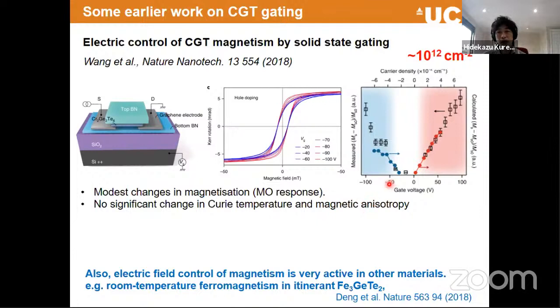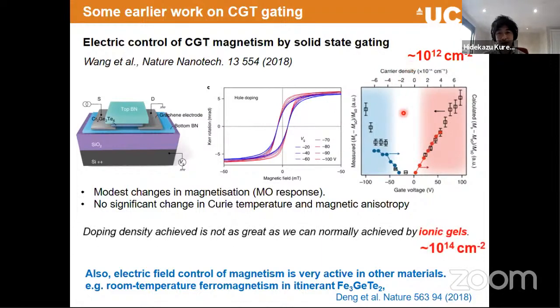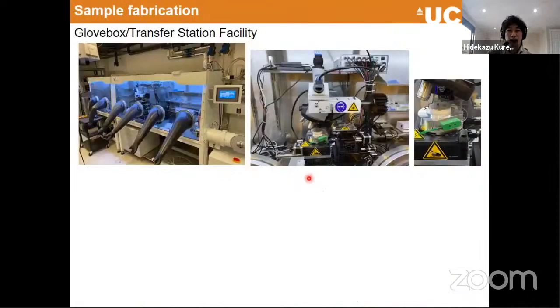And we were doing the same thing at the same time, and we know that the doping level that we can achieve by this solid state gating is about 10^12 per square centimeter. At the same time, we did the same experiment using a different gating mechanism, and this ionic gel can normally achieve much higher carrier injection. That's probably two orders of magnitude stronger than this. And we saw a very different behavior, which I will show in a minute. I just want to give you some flavor of what we are doing every day.